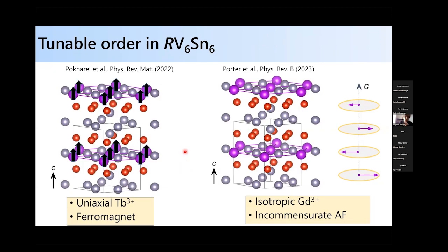So to summarize the tunable order that can be realized, looking at these two extremes: if you put terbium in there, we can interface the kagome net with a strong uniaxial ferromagnet. And if you go to the opposite, more isotropic limit with gadolinium 3+, then we realize an incommensurate antiferromagnetic state. For this incommensurate modulation, our best model right now is a moment-modulated state likely driven by nesting of small pockets along the c-axis via RKKY exchange. But more experiments need to be done to really validate this type of model.